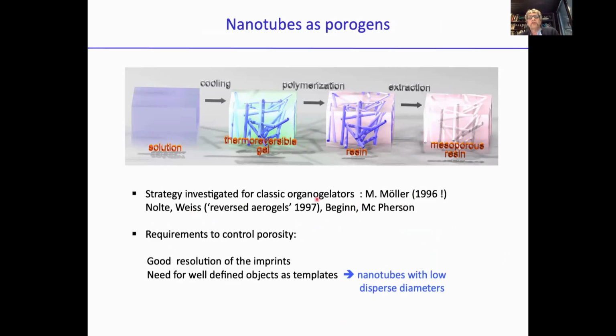But the solution is very simple. We start from an isotropic solution, and when it cools, it forms these gels, which are still thermoreversible if you have a regular solvent. But instead of a solvent, we took a mixture of cross-linkable monomers, and at this stage we perform a photopolymerization. So we obtain a resin that contains all the objects, and then we leach them out. We dip it in a dissociating solvent to take out the self-assembled molecules, and it leaves these white objects that are in fact empty pores.